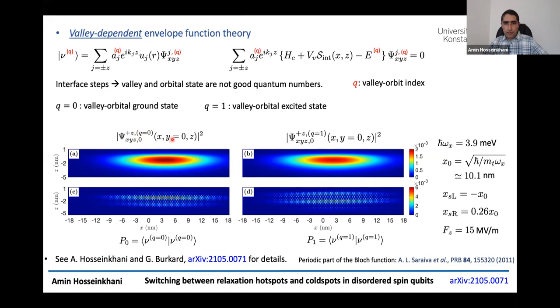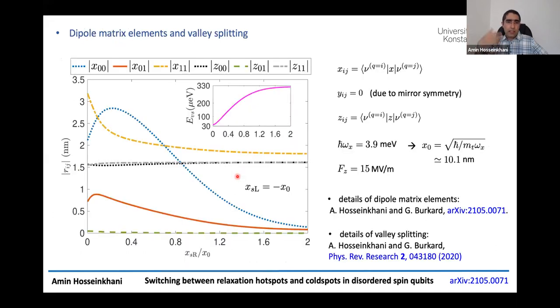As a result, we have both intervalley and intravalley dipole matrix elements. One example shows the x and z dipole matrix elements as a function of step position: as we push a step away from the quantum dot center, the in-plane dipole matrix elements decrease, whereas the out-of-plane dipole matrix elements are nearly independent of step position due to the symmetry along the x-axis. We can also calculate the valley splitting as a function of step position — it is well known that steps can significantly reduce the valley splitting.